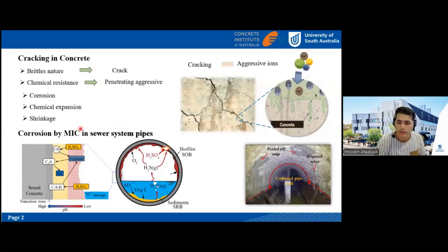Another important problem, which mostly happens in sewer system pipes, is microbiologically induced corrosion, or MIC, which happens in this environment because of the activation of microorganisms. In this environment, the hydrogen sulfide from the sewer is transformed to sulfuric acid, which reacts with the concrete structure and causes corrosion, changing the concrete into a very soft material.